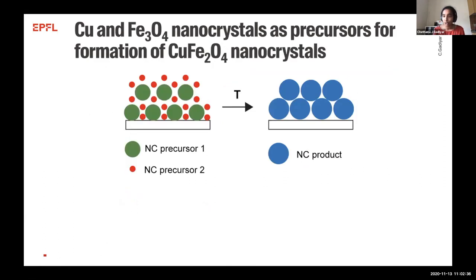So an alternative approach that I show in my work here is based on thin film technology. So making thin films of these multinary metal oxides. And what we do here is to use shape and size controlled nanocrystals as a precursor so that these nanocrystals can react with each other to form the ternary oxide. And in this study, we focused on copper and iron oxide nanocrystals as precursors, which react with each other to form copper iron oxide nanocrystals. This is mainly because copper and iron oxide is a very well studied system, and there is a lot of literature available for synthesis of shape and size controlled copper as well as iron oxide nanocrystals.